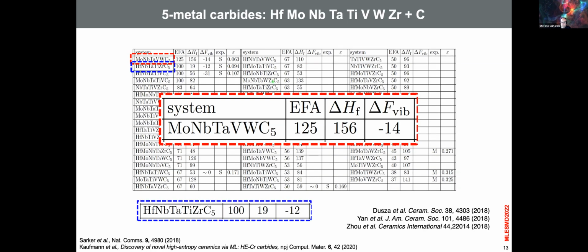Okay, now let's use it to study new materials, because at the end theory is as good as we find new systems. So we're interested in metal carbides. Here you have refractory metals, so you have 8 of them, plus you add some carbon, and then we ask which are the 5 metal carbides that will form. We already knew from oxides that the sweet spot was 5 metals, as I showed before from the unavoidable disorder. So we know that we need to have 5 species shuffling. So for each one of these we have a 5-metal combination plus carbon.